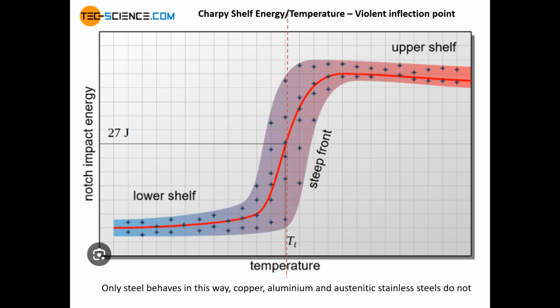So on this graph, you have on the y-axis, notch impact energy, and on the x-axis, temperature. In this case, the temperature goes from, on the right-hand side, room temperature or higher, and towards the center of the graph, or the intercept between temperature and notch energy, you have lower temperatures of, say, -20, -40, -80. This is a material where at room temperature, so this would be a typical JR type material, you would measure its impact energy, and it would be over 27 joules at room temperature. As you cooled the material down at around 0 degrees, -10, the Charpy impact energy that you would measure on that machine would drop, and then it would reach its lower shelf energy, where it wouldn't decrease any further, even if you cooled it down more.